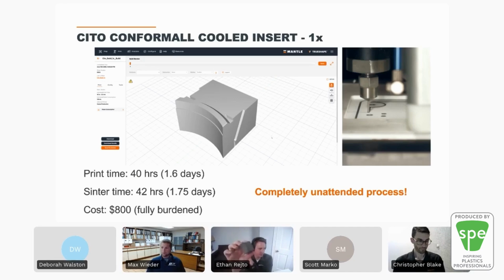This is going to print in about 40 hours, so about a day and a half. It's going to go into that oven for about a day and a half, and then for a fully burdened cost of about $800 to print just one of these. One thing I did want to include, of course, is that's a fully unattended process. So, this is what's coming out of the process. Maybe you give this to your toolmaker to do a little bit of finishing, grinding, or tapping of water lines or something like that.